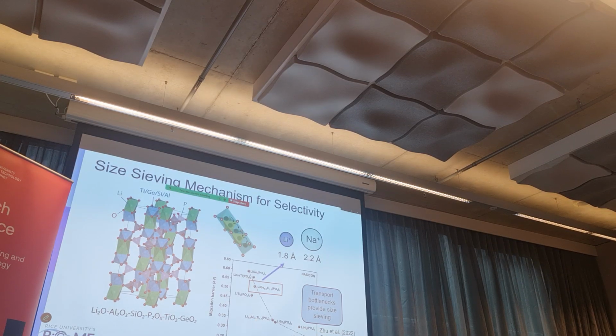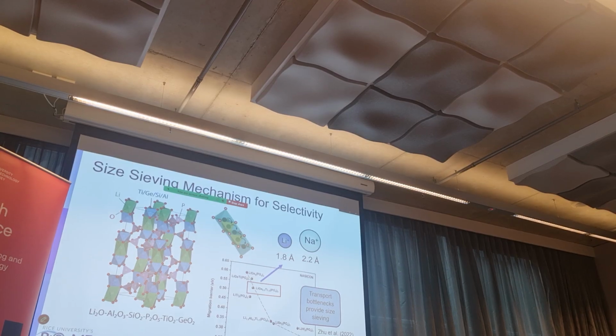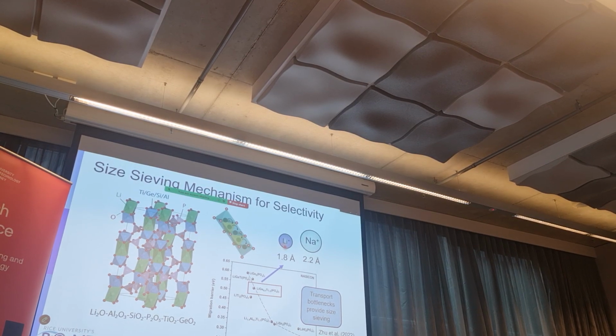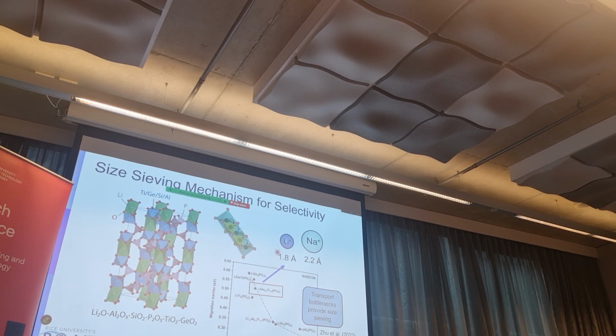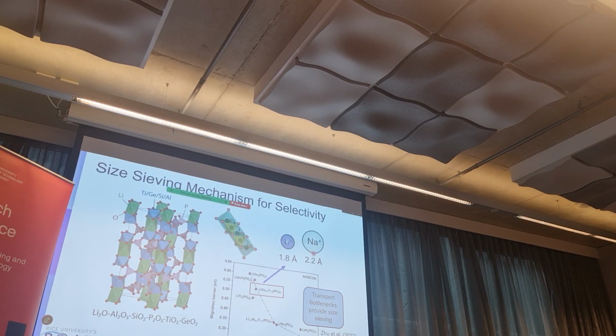Our solid state electrolyte is roughly similar to what you see here from this paper, about a little under 2. If you look at lithium, it's 1.8 when dehydrated, so it can go through, but sodium when dehydrated is 2.2, so sodium cannot go through. This is why.